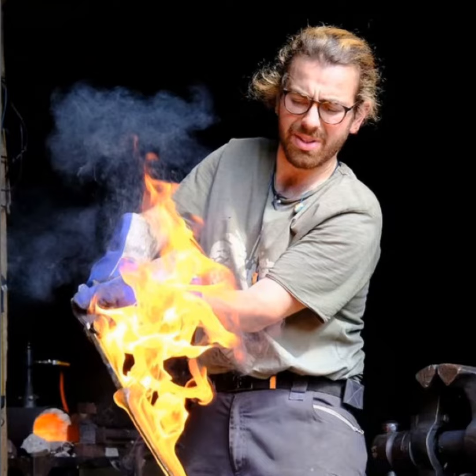So after that, when I have even bevels, then I can go to the 180 grit synthetic stone. But if I have to remove major, well, I used the word before. I don't remember it right now. Not flat spots, low spots. When I have low spots on the bevel, then I go to the Atoma 140, and it is a really, really aggressive stone. So you can even out the bevels first, and then I'm just progressing to a 400 grit, 800 grit, 1000 grit, and then I start using my Japanese stones.